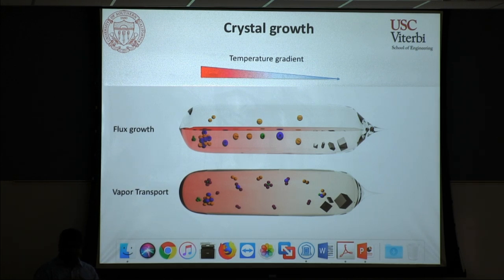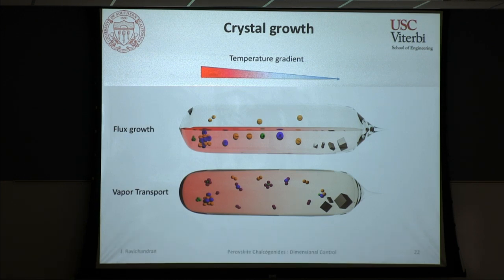Even if you did, it's very hard to analyze them because very subtle changes in the perovskite block thickness can immediately change the phase that you're looking at. So that's why we wanted to grow single crystals to make sure that it's reliably uniform in structure and composition. So we used a couple of methods. The one method that is going to be relevant for this part of the talk is the flux growth method.